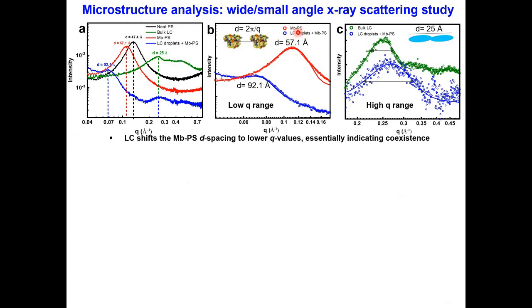But when we combine this protein conjugate with liquid crystals, you can see that this peak shifts to lower Q values. And if you remember correctly, D was inversely proportional to Q. So as Q decreases, that means D increases. So you are increasing the protein-protein distance from 57 angstrom to 92 angstrom. So what does that mean? That when you include liquid crystal in between protein, the liquid crystal acts as a solvent and it separates the protein molecules further apart.